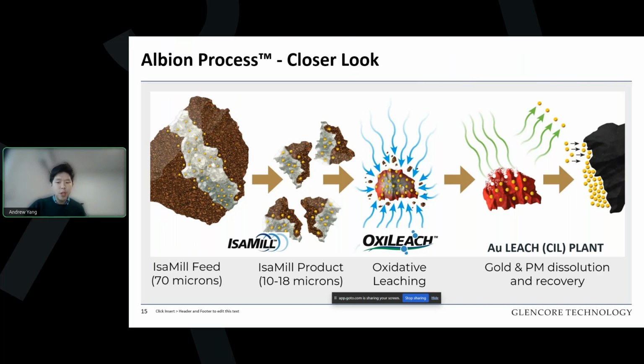We have a slightly more finicky bioleaching process with a longer residence time of the bacteria, or we can have the Albion process. Here we can optimize the grind size so that we produce those microcracks, and then we can send it to our oxy-leach reactors. That eliminates the impact of passivation layers, because of those microfissures, those microcracks, and then we're able to dissolve away a sufficient amount of that host mineral in order to liberate these different host metals such as gold.